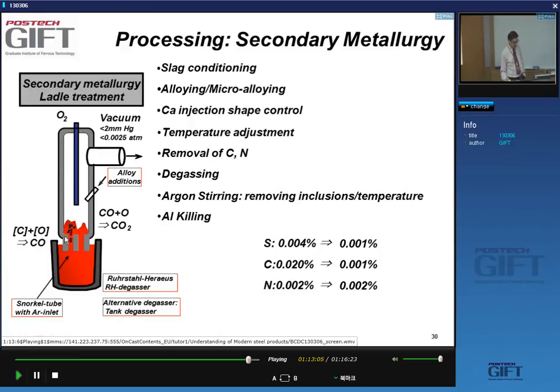The reason is that you continue removing the carbon, getting very low levels of carbon, in the following way. This is your ladle, right? The one we just saw, with the molten metal. You put it in this vacuum tank, and this vacuum tank has two tubes at the bottom, and in one of the tubes you inject argon. This tube is called the snorkel tube. So what happens if you inject argon?